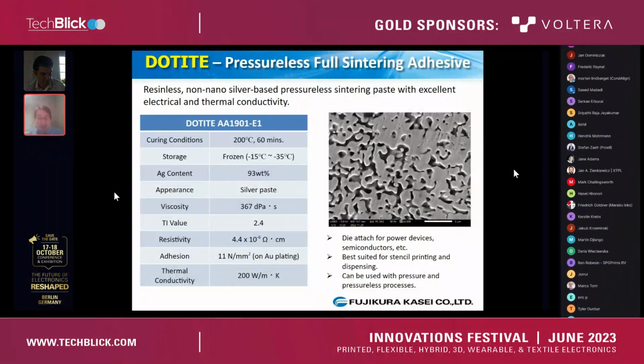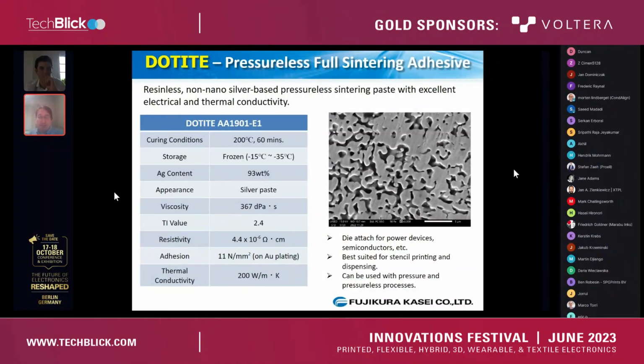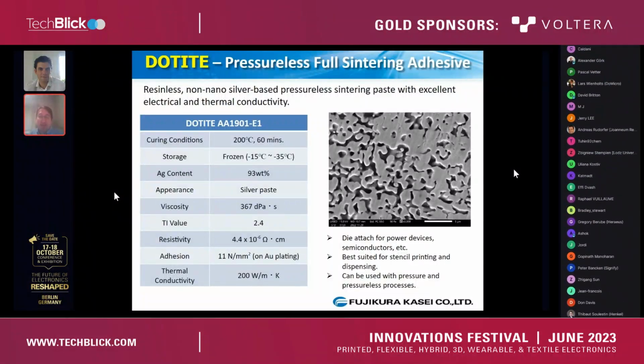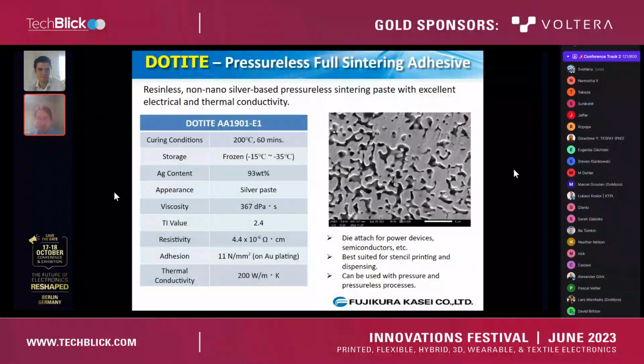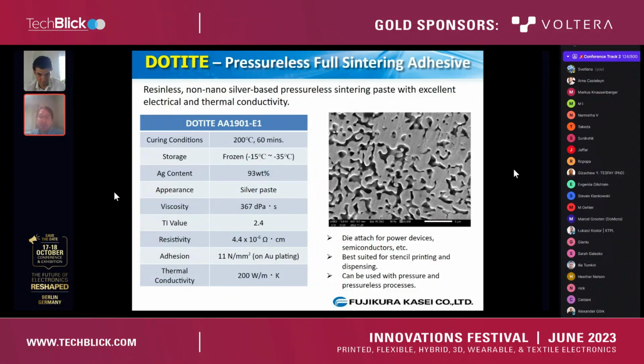AA1901E1 is 93% silver and is a resinless adhesive. Because it's resinless, the applicable substrates are limited to primarily gold or silver, but its adhesive strength is provided by the sintering process alone. It can achieve 11 newtons per millimeter square of adhesive strength when cured at 200 degrees for 60 minutes. It has a high electrical conductivity, 4.4 times 10 to the minus 6 ohm-centimeters, and excellent thermal conductivity, 200 watts per meter Kelvin. It can be sintered with pressure or without, offering the benefit of a sintering paste without requiring additional equipment, and a versatile die-attached material for power devices, semiconductors, and similar applications where both electrical and thermal conductivity are necessary. Okay, next slide, please.